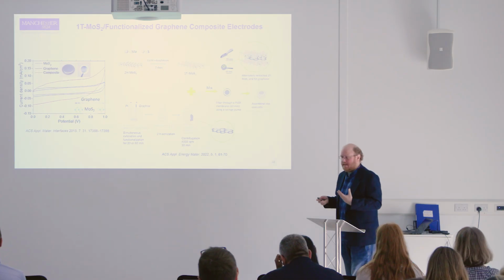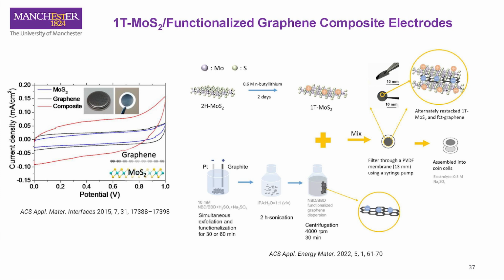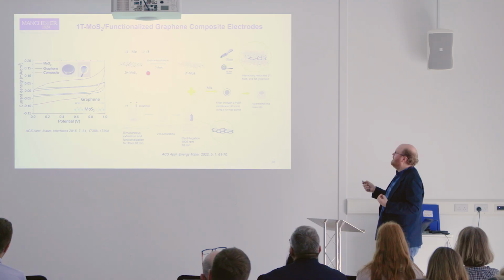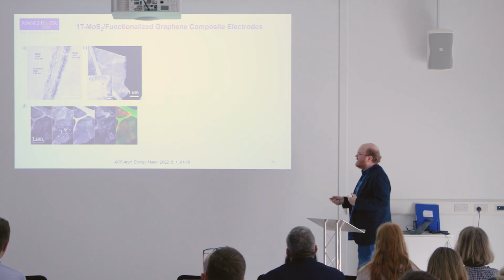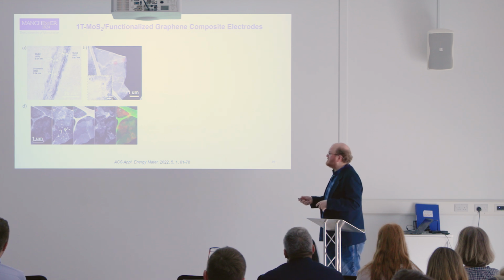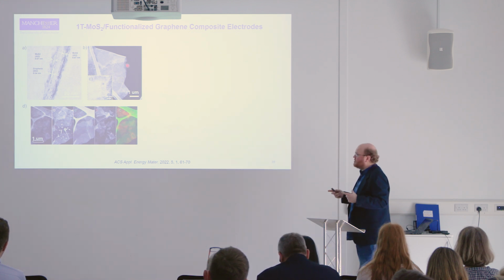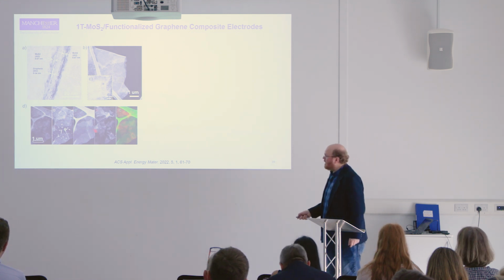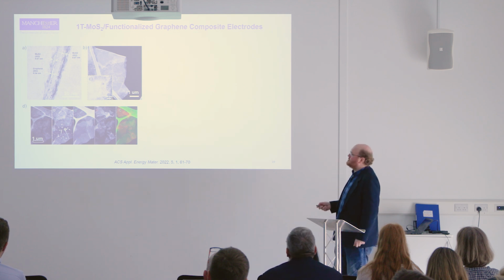We've expanded that to looking at, now if we functionalize the graphene or if we functionalize the MoS2, can we get even further benefits? So here we were taking MoS2 and chemically exfoliating it by intercalating lithium. We were taking electrochemically exfoliated graphene and mixing them together to get this composite structure where you've got stacked graphene and MoS2. You can see from TEM how these stack together. You tend to get very large graphene sheets with smaller MoS2 sheets decorated all over the surface.